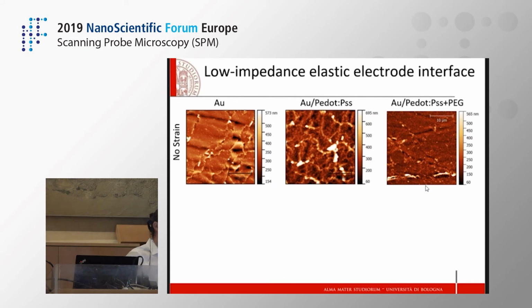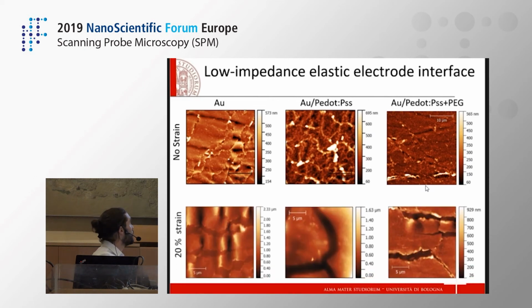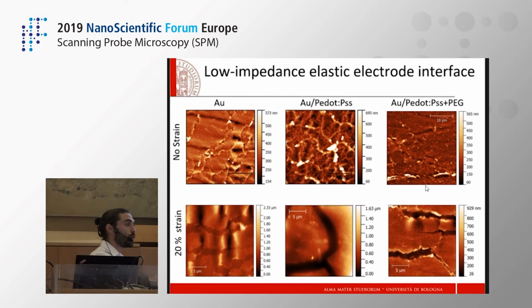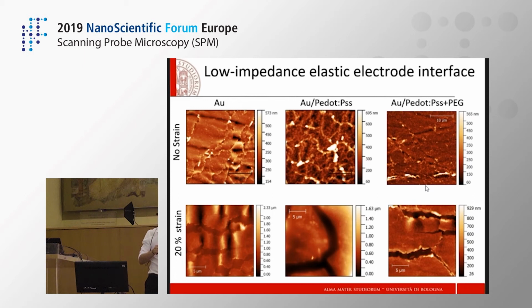Starting from the situation without any strain, we can see that there are surface height modifications that could be seen in all three of the images, and are probably due to the gold layer underneath the micro-cracked gold layer. In this case, when we introduce the strain, the gold basically starts to form cracks that are orthogonal to the strain but are still a few micrometers.